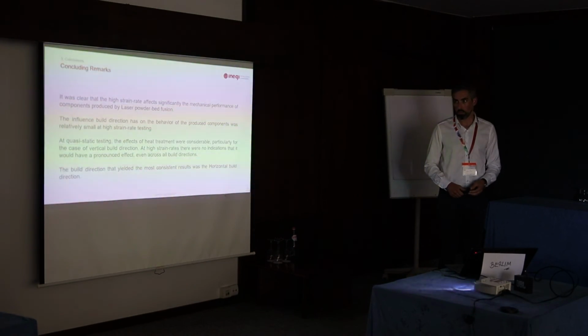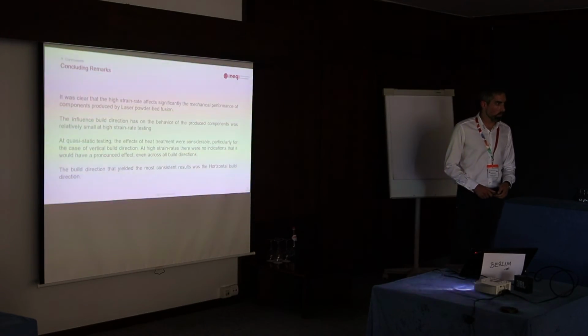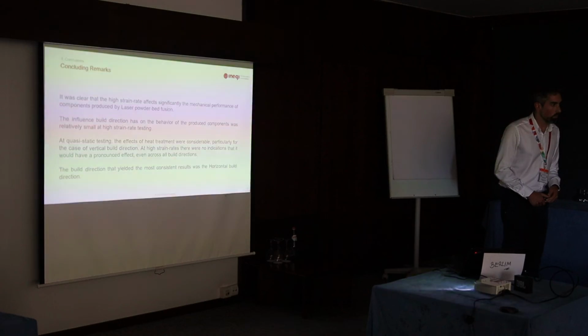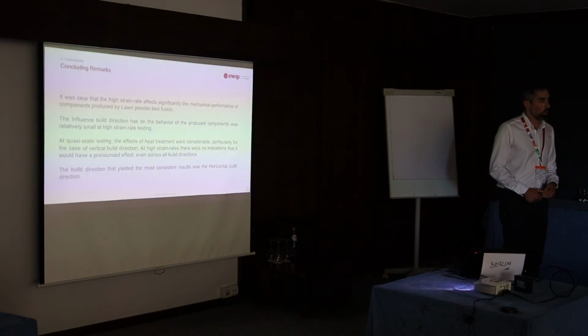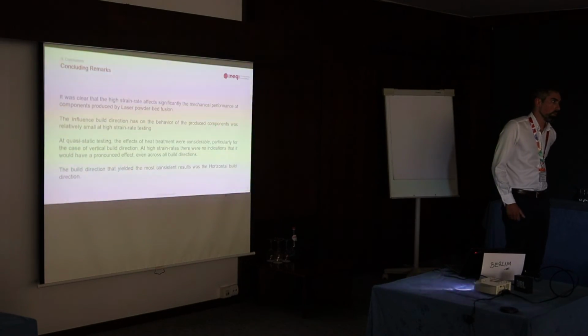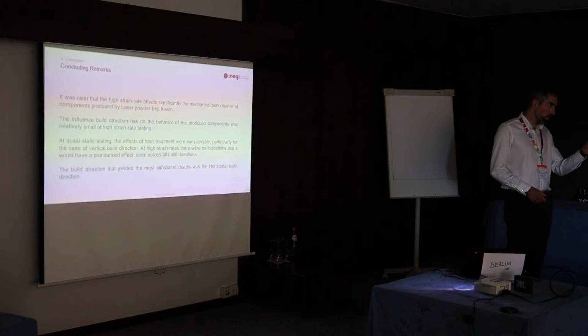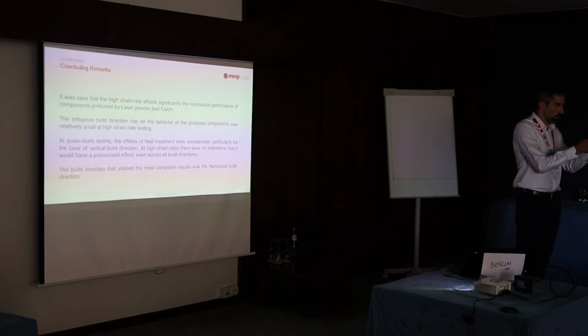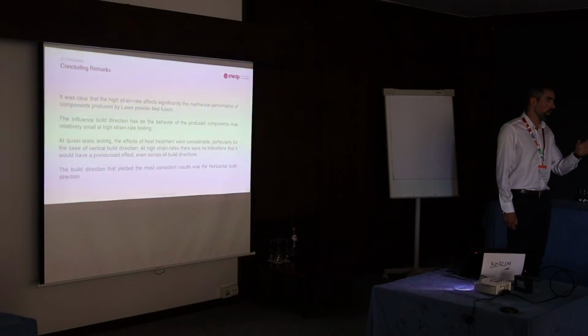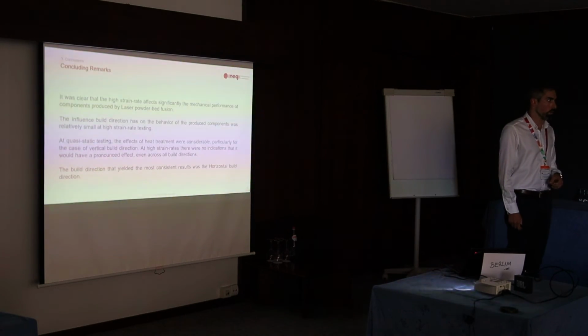Are there questions from the audience? Yeah. How do you measure the strain rate? For high strain rate, how were you measuring the strain rate, and what was the strain rate? We were using the high-speed camera, so digital image correlation. So what was the strain rate? Like 300. Okay. It's a range, but it's between 290 and 310.